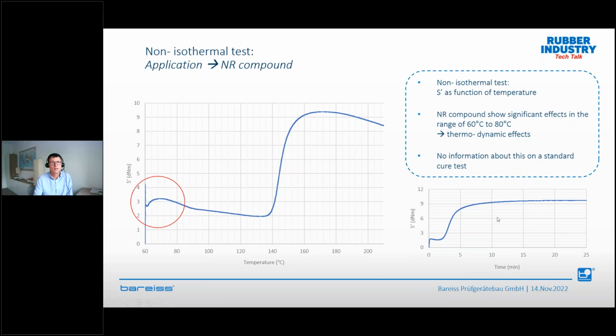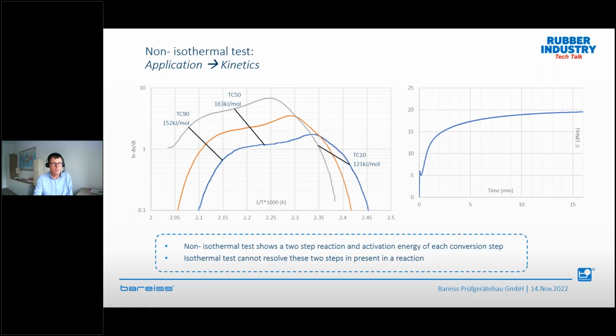Also for the non-isothermal test, the blue curve, orange curve and gray curve are the three heating rates, torque values, when we plot the conversion as a function of absolute temperature. And the black curve connects TC90, TC50 and TC10.